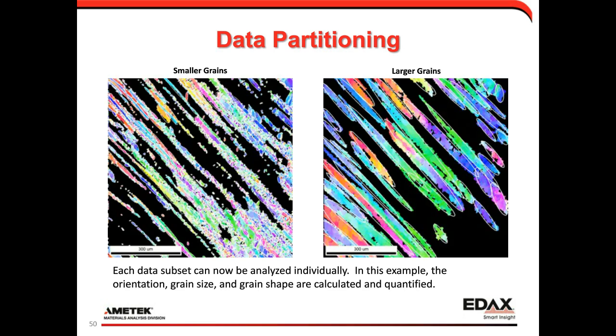And then we can create a subset by either side. So I'm showing here the orientations of the smaller grains on the left, the orientations of the larger grains on the right. In addition to the orientations, now I fit shape ellipses to get an idea of the grain shape. Obviously the smaller grains are much more equiaxed. The larger grains have a lot more of that needle shape aspect ratio and alignment than the smaller grains do.